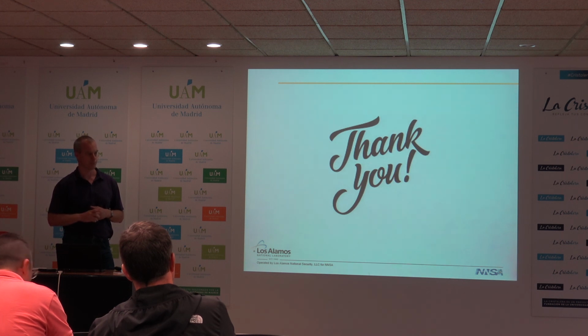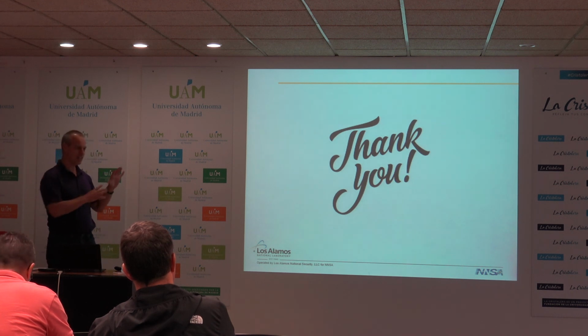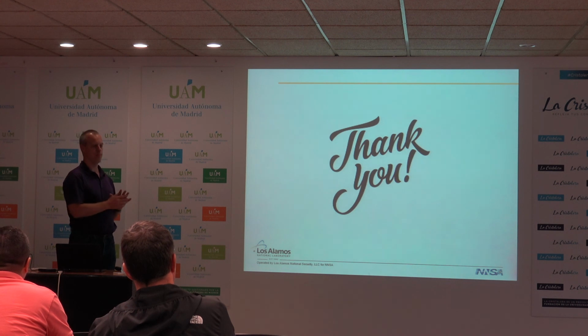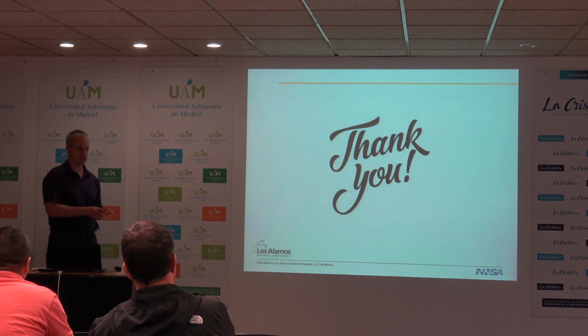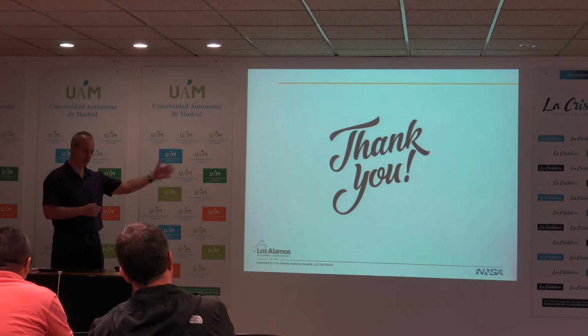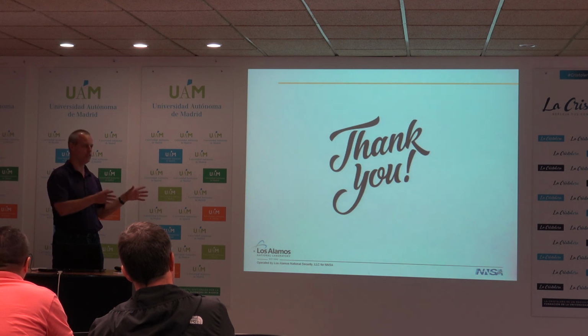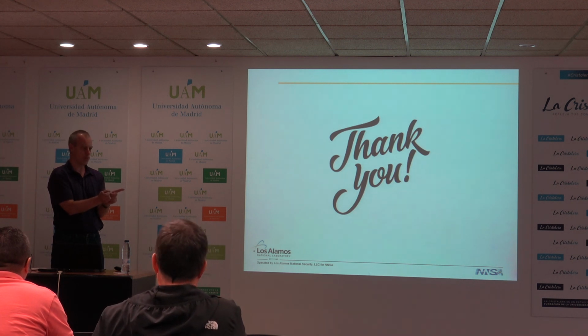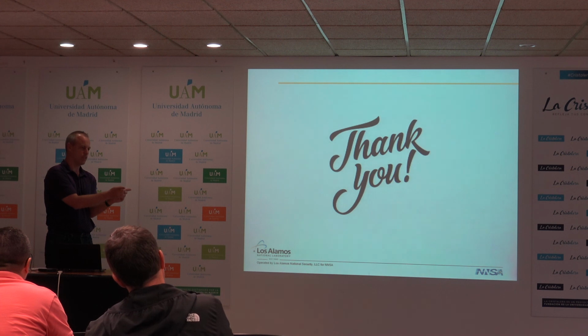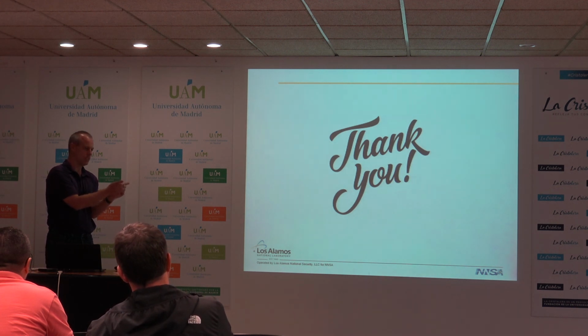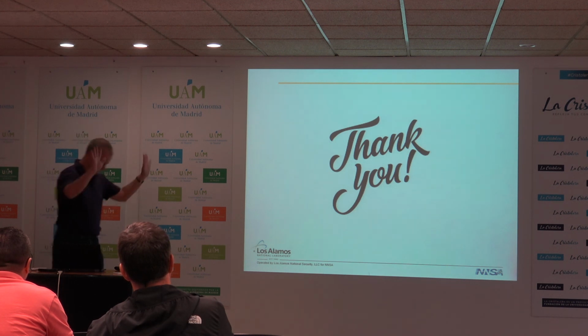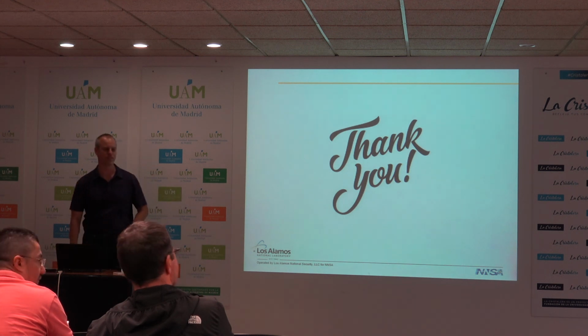So this makes its nematicity very mysterious then, right? Yes. I try to say it's a nematic-like response. Whether it really is electronic nematic, I don't know. And one of the other things I didn't mention was that we see the same response in the B1G and the B2G channels. Whether we make a device with rho A and rho B, or make another device at 45 degrees and look along 110 and 1 minus 10, we see the same kind of response as well. So this is almost universal behavior. I agree. Yeah.